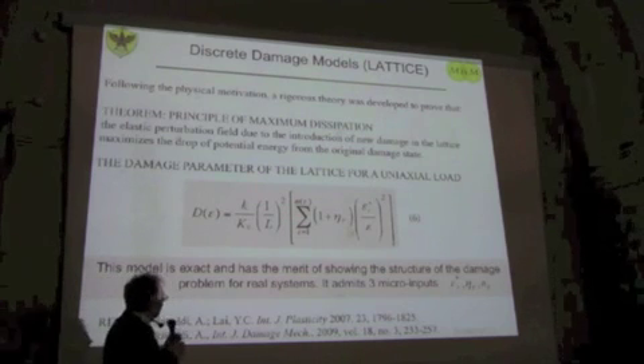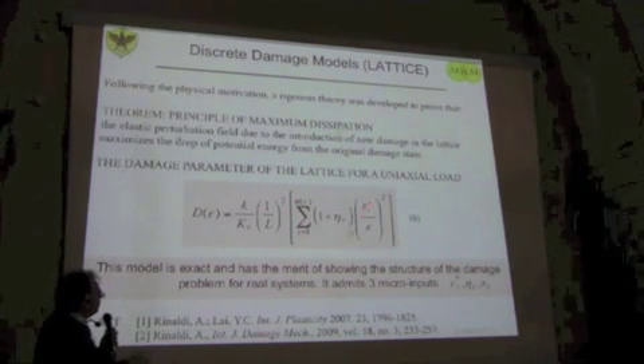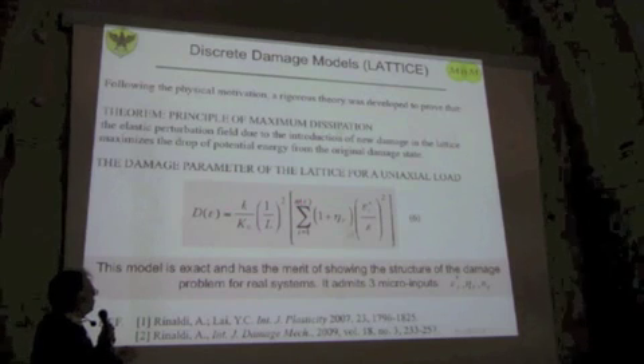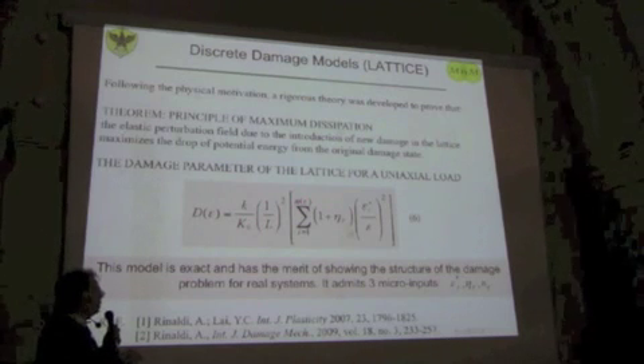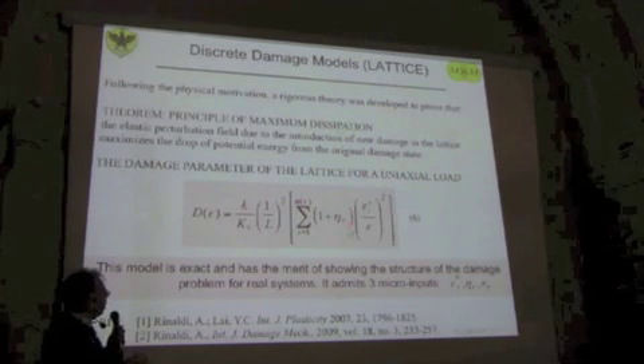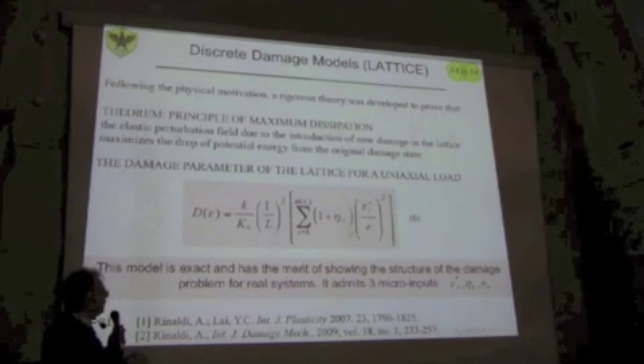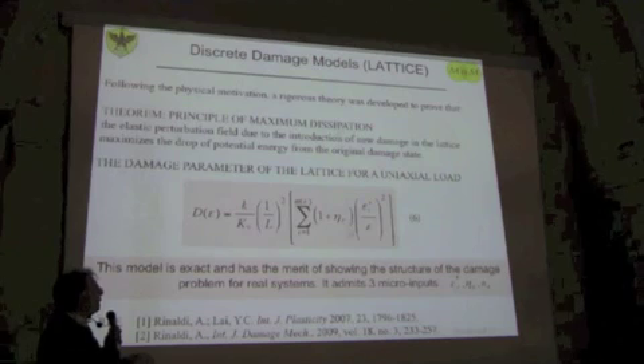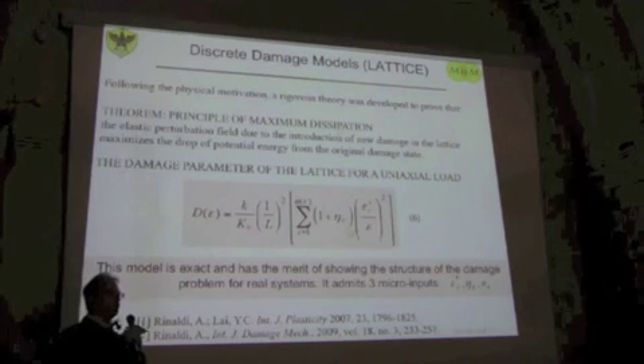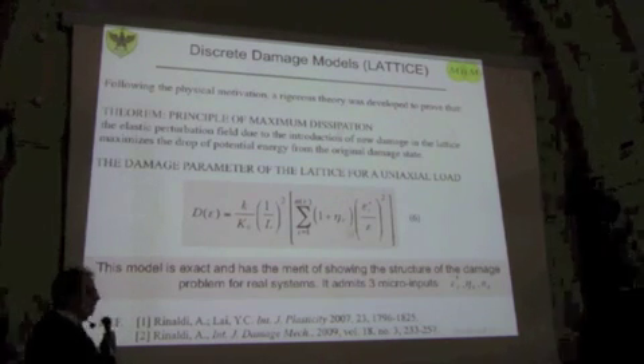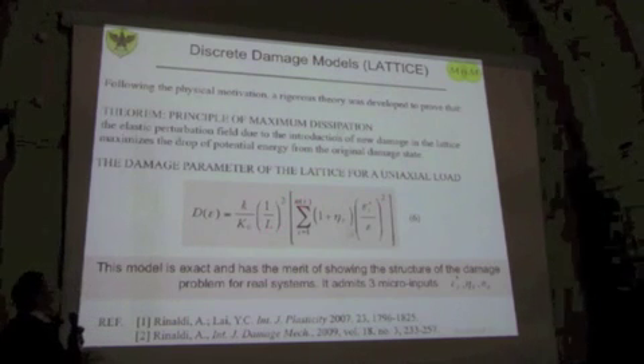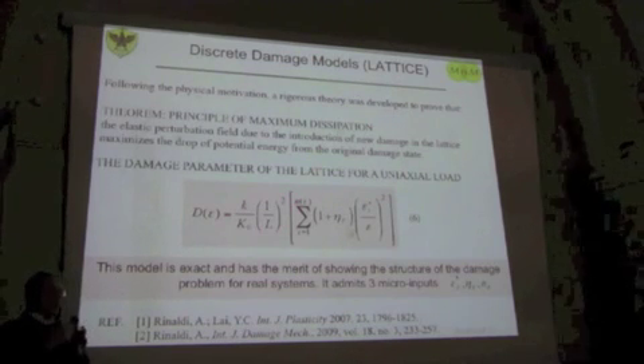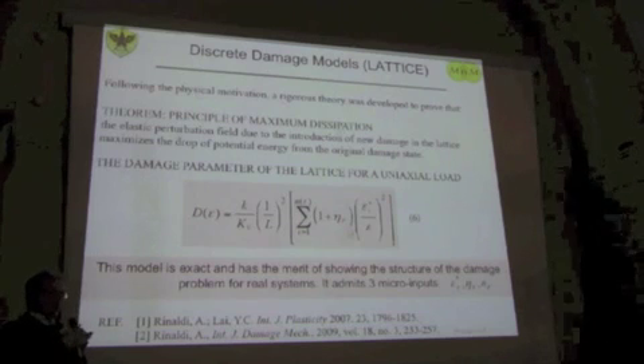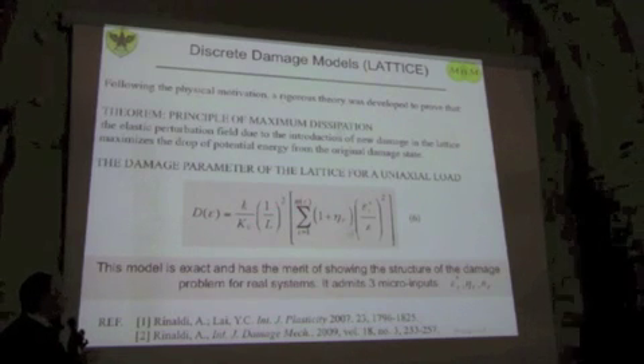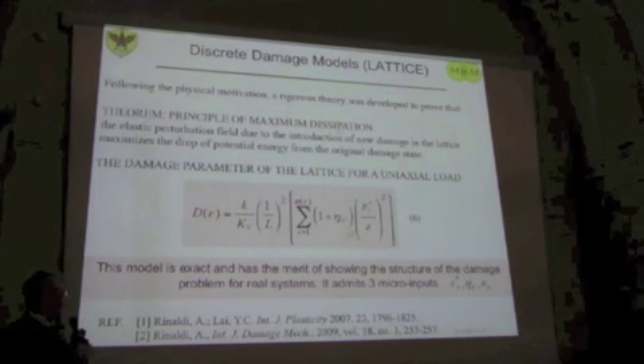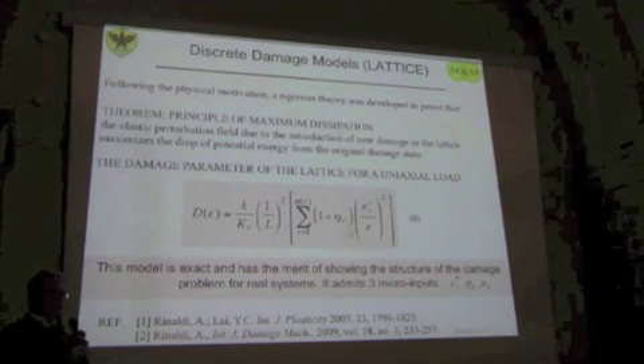Now, let me just point out to you that there are 3 random quantities that enter in this model. The number of broken bonds, and for each broken bond you have a parameter eta, which is a redistribution parameter, and the microstrain of the link that broke, so the critical strain of that link. Why am I saying this? Because this is a nice mathematical tool, it's the reference point for us to reason, but it's very difficult in practice to know these quantities, okay?